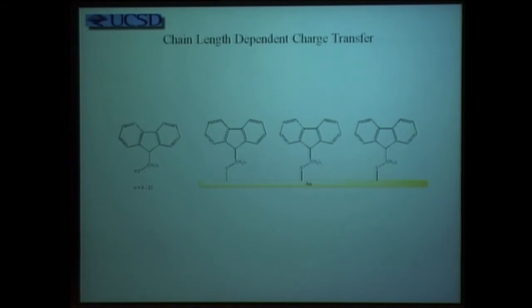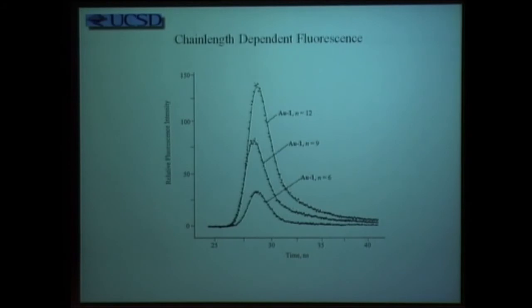Now, if you take that molecule and you make a coating equally thick of each of these materials, you have what's shown here. That is for 12 CH2 groups, for 9 CH2 groups and 6, the intensity of the emission, the fluorescence that comes off of that system, is in direct proportion to the length. What this tells you is that the distance does matter significantly in making these shell core clusters, as it did in doping of the semiconductor to begin with.